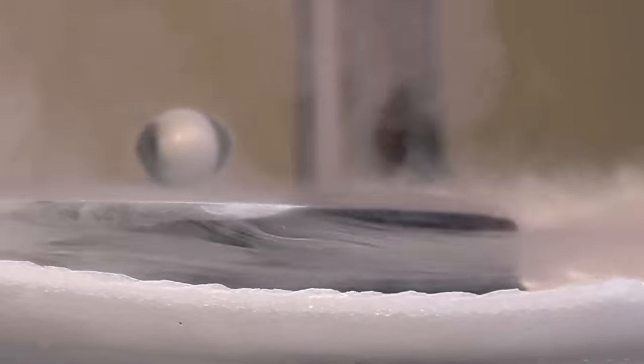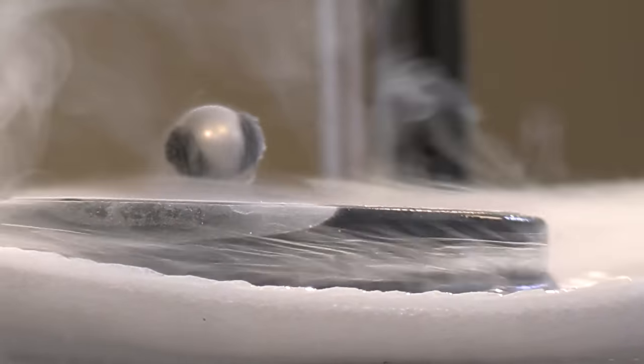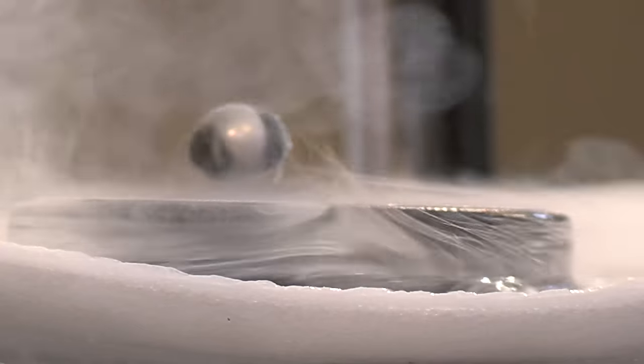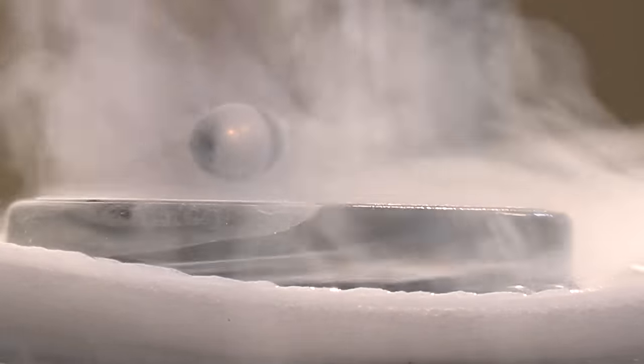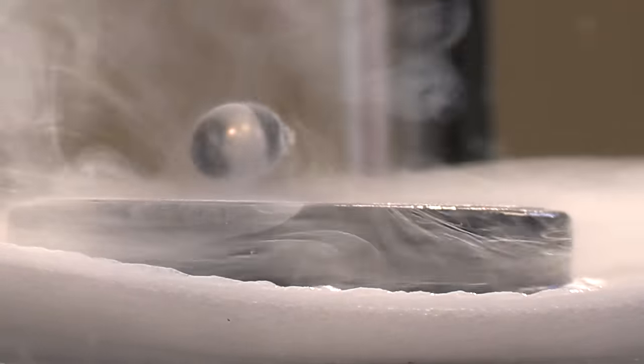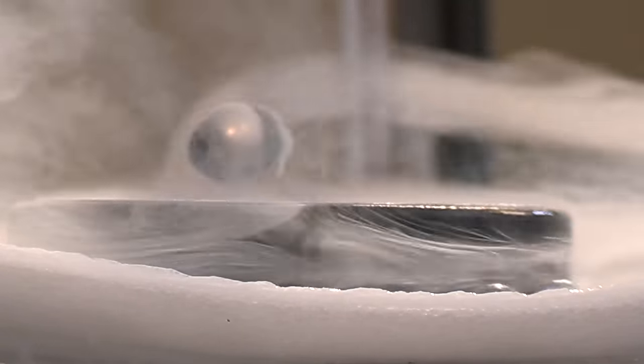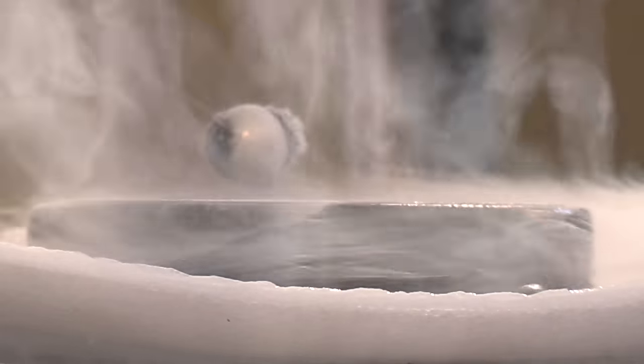So it's not magic. What's really happening is the magnetic field is trapped inside the superconductor. So it initially doesn't want to let any in, but if any does get in through a defect zone or an imperfection, then the surrounding superconducting material generates eddy currents in the material that create a magnetic field that physically lock the flux lines from that magnet in place, and so it can't move. Now, if you push it hard enough, it'll move, but in general, if I give it a little nudge in either direction, it doesn't really want to move.